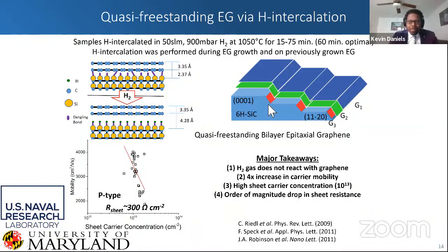And in this case, the additional growth that we see on the step edges is actually helpful, because now, instead of having 1, 2, and 3 layers of graphene, we have pretty conformal 2 layers of graphene with a little bit of 3 layers present. And we see a 4 times increase in carrier mobility as a result. So we have this very high sheet carrier concentration, 10 to the 13 per centimeter squared, and an order of magnitude drop in sheet resistance. So this is a very conductive material and a perfect substrate to fabricate additional materials on top of it.